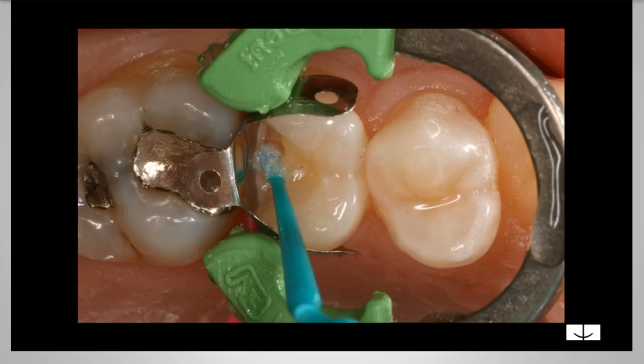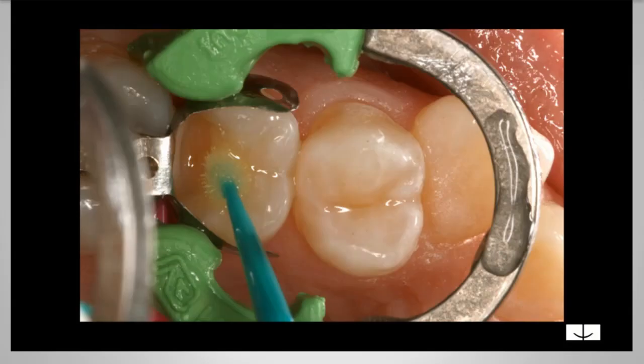Now, some people use Gluma. That's great. Whatever you're using, I would use a re-wetting agent if you're doing an etch and rinse system. Once that's done, I air thin that down, and then I start to place, in a 5th generation, the primer and bonding agent in one, and I coat that over and over again. I air thin it and I coat it again. I probably put in 2 to 3 coats, and I'm scrubbing it in. The scrubbing really is effective in getting those resin tags to penetrate deep into the dentin and into the enamel.